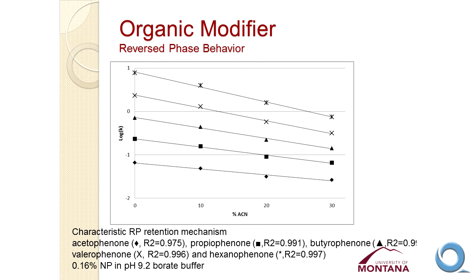We've characterized them in a lot of different ways. One thing that we did was to look at retention, or the logarithm of the retention factor, as a function of the concentration of acetonitrile added to the system. And these are for those same five alkyl phenyl ketones. And we see these nice linear relationships here.